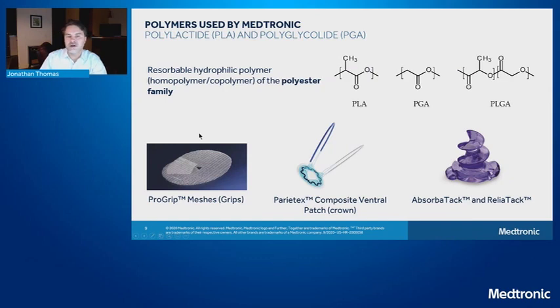Let's talk a little bit about absorbable polymers. Polylactide and polyglycolide are 2 different polymers in the polyester family. They're absorbable, and by absorbable, I mean that they have a backbone that is available to be attacked by hydrolysis. So water can go up to this backbone and start to digest the polymer and break the chain. We can make copolymers of PLGA, where individual mer units, right here, are randomly arranged or in a more orderly fashion.